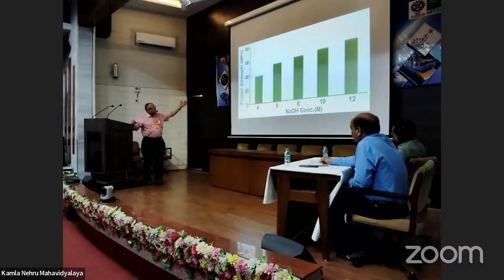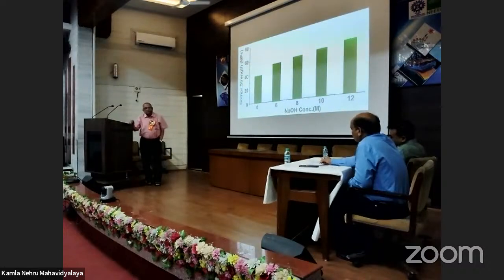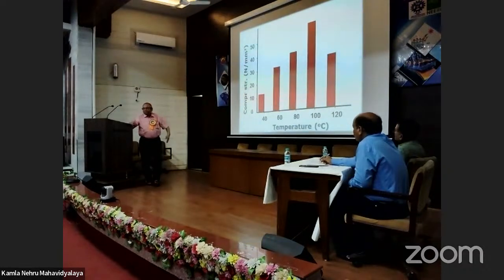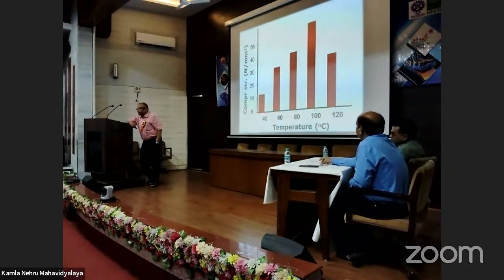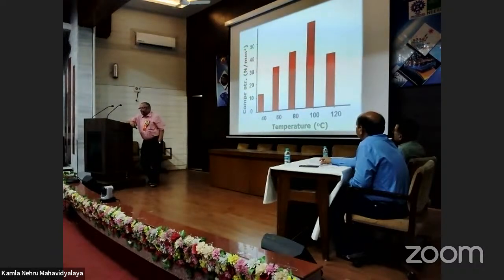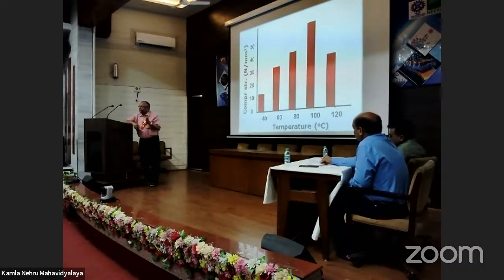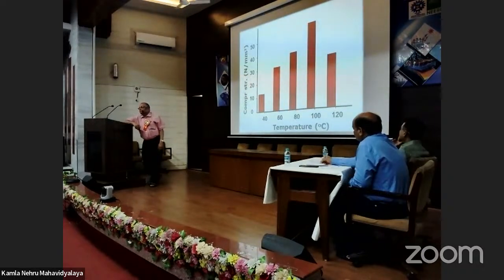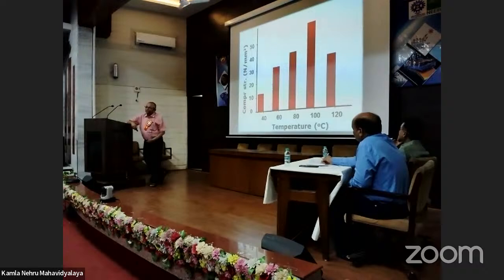Here you see that compressive strength increases when you increase the concentration up to 12 molar. Compressive strength also increases with the temperature, but there is an optimum temperature. Normally, Portland cement, when you add water, gains strength, it takes time. In geopolymer cement and concrete, it immediately increases, but if you heat it up to around 80 or 100 degrees centigrade, it has twice or thrice as high the compressive strength of the Portland cement.